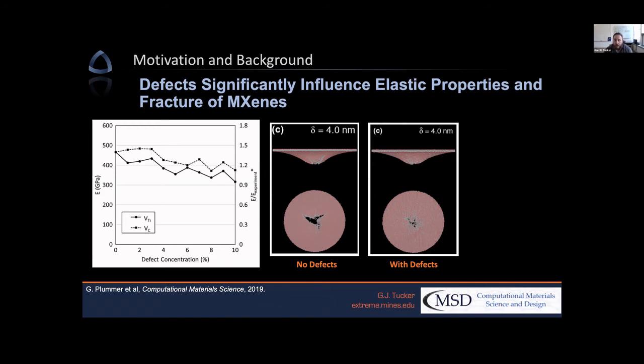Once again, this supports the notion that these MXene monolayers are not pristine. They probably do have these point defects in them, and we can start to probe that information with atomistic modeling. And so shown here in the middle is a snapshot of when the MXene starts to break, both with and without defects. And you can see that there obviously is a very strong dependence of the fracture characteristics when we consider point defects in that MXene monolayer.